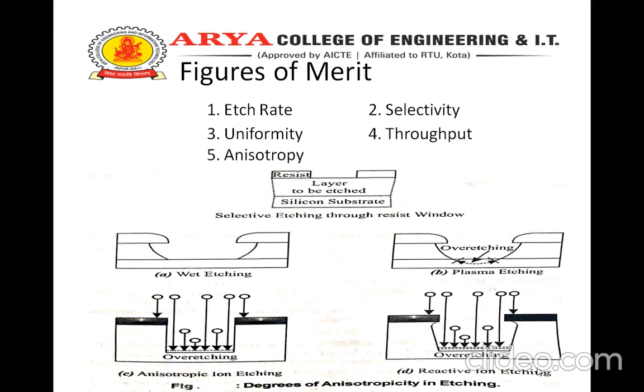Next is anisotropy. Anisotropy pertains to the ability of the etching process to attack the layer in a directed manner. Two distinct mechanisms normally coexist in the etching process in IC technology: chemical etching, which is essentially isotropic, and ionic etching, which is directed or anisotropic, the directivity being provided by the directed electric field. In fine line VLSI fabrication, the latter is extremely important. Consider the situation where a feature is to be etched on a wafer. If the etching is isotropic, the etching while acting vertically downward on the specified area...